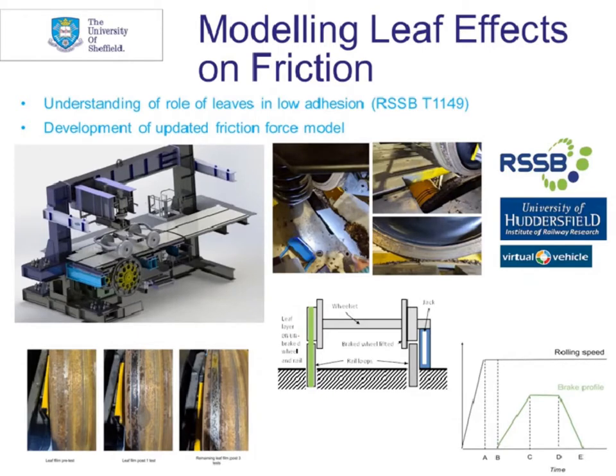We've done a number of projects looking at modelling the effects of friction in the wheel-rail contact, initially looking at what we call wet rail, so it's mixtures of small amounts of water and oxide in the interface. And then more recently, we've extended that approach to look at leaves.